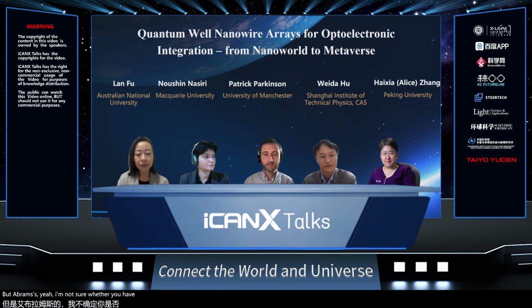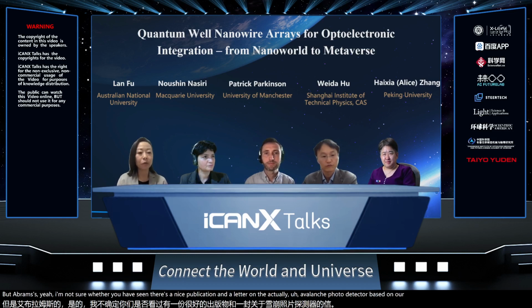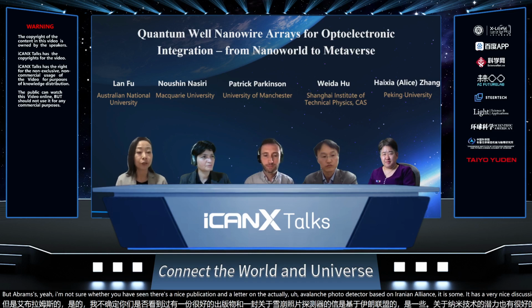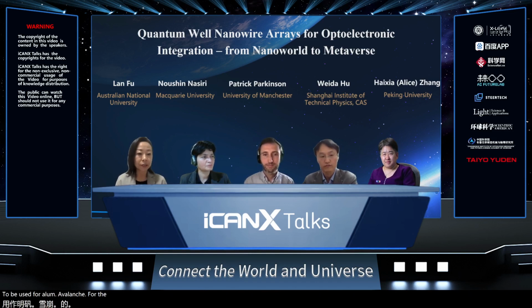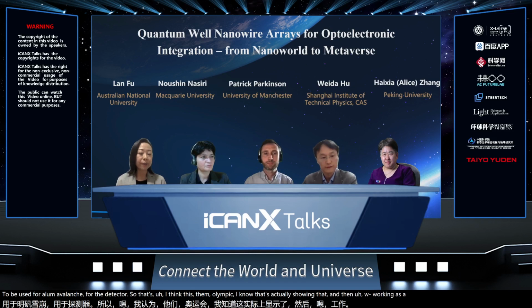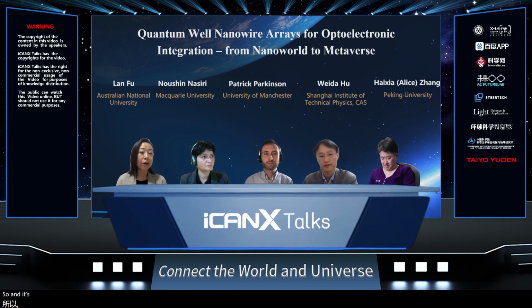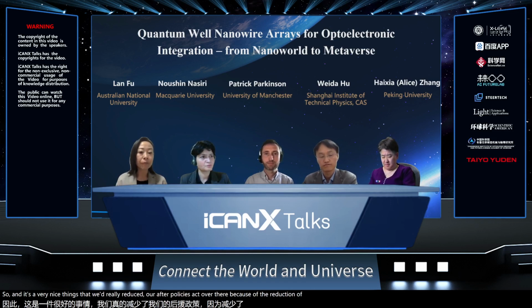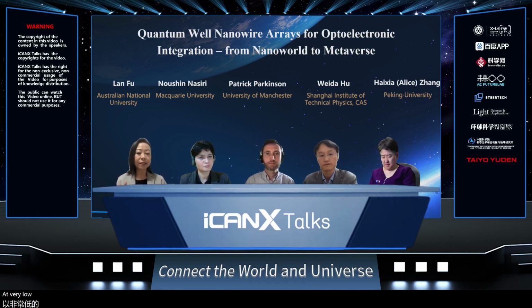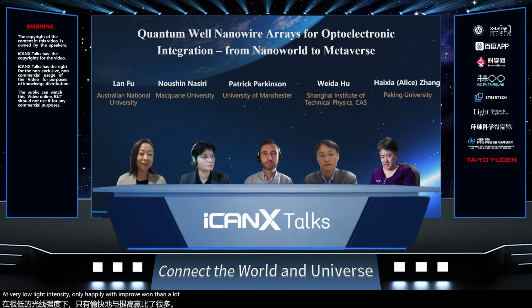I'm not sure whether you have seen, there's a nice publication in Nano Letters on an avalanche photodetector based on array nanowires. It has a very nice discussion there about the potential for nanowires to be used for avalanche photodetectors. I think that's the only paper I know that's actually showing nanowires working as APD in Geiger mode. The very nice thing is that it really reduced the afterpulse effect because of the reduction of the material volume. So this avalanche event at very low light intensity only happens with probably one nanowire, right? So basically, you really don't have all the other problems from the bulk material.